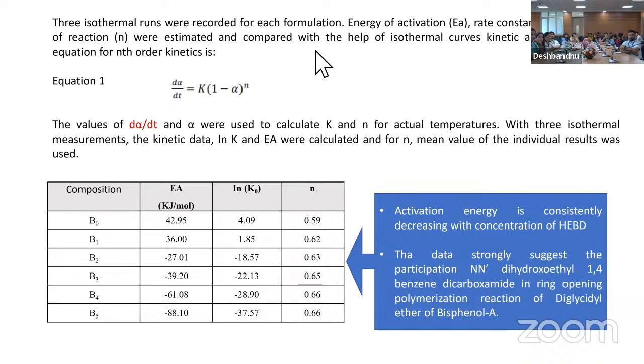We can see the energy of activation in kilojoule per mole is, for B0, 42.95, then 36, 27. It is decreasing up to the B5 formulation. We get the order of the reaction. So these data strongly suggest that our monomer is participating in the reaction. It is not just acting as a filler, and it is enhancing the mechanical properties when we test it.